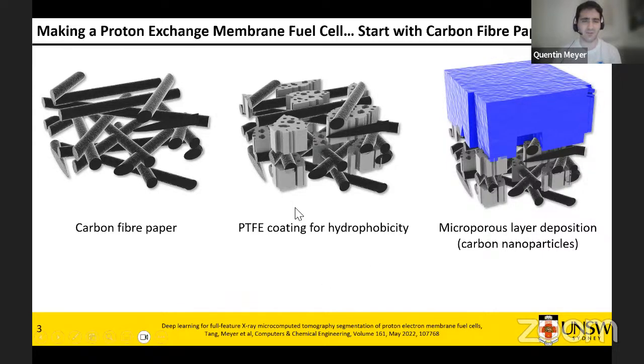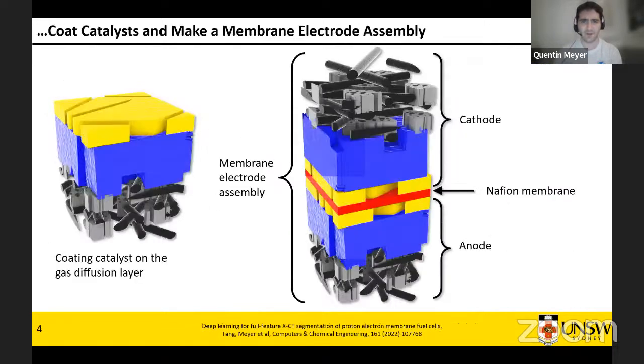After that, you want to make it hydrophobic because fuel cells produce a lot of water. You want to remove it, so you coat it with some PTFE or Teflon material. After that, you add a thin layer of carbon nanoparticles, which is called the microporous layer. On top of that, you want to have your material that creates the reaction. So you put some catalyst, that's the material in yellow, and then you sandwich it on both sides, and you have a cathode, a membrane, an anode, and altogether that gives you hydrogen fuel cells.